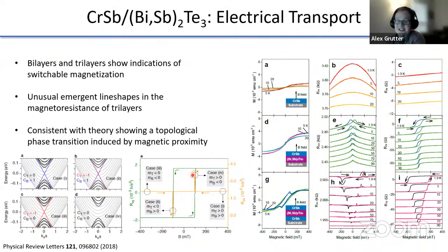Oh, that's a good question. Chromium antimonide is pretty complicated. Not only that, but there is some evidence in another study we did that I didn't have time to talk about, that you actually change the magnetic state in the chromium antimonide as you interface it with these topological surface states. This has shown up in a number of different studies, actually. I think Nitin Samarth had a study; I'm not sure if it was Nitin. There was definitely a study about how interfacing yttrium iron garnet with the topological surface states may actually change the magnetization in the yttrium iron garnet, and the interaction goes both ways. So I think the answer to your question is yes.